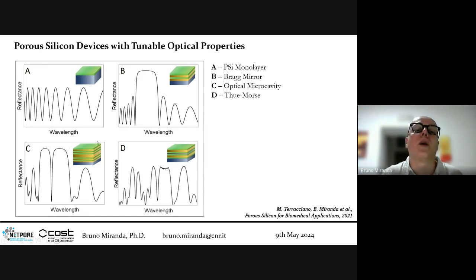Or you can have an optical microcavity with very sharp resonances, as in case C. You have the optical microcavity here, with a very sharp dip in the reflectance spectrum that can be very sensitive to refractive index variations for biosensing. Or you can have very complex shapes such as this one, where you can tune the optical properties according to what you need for your biosensor.